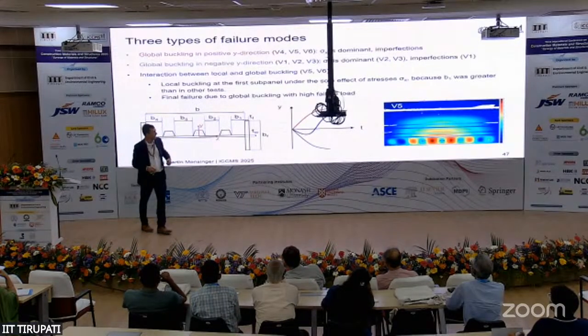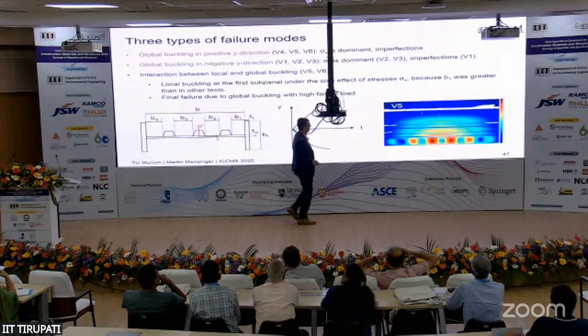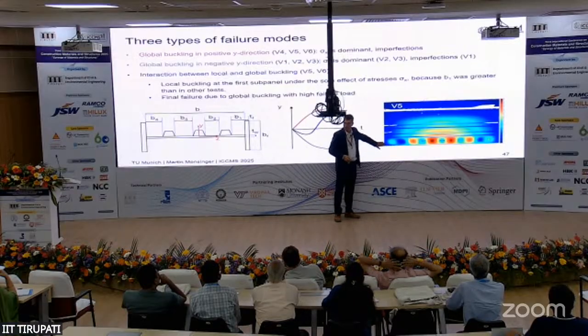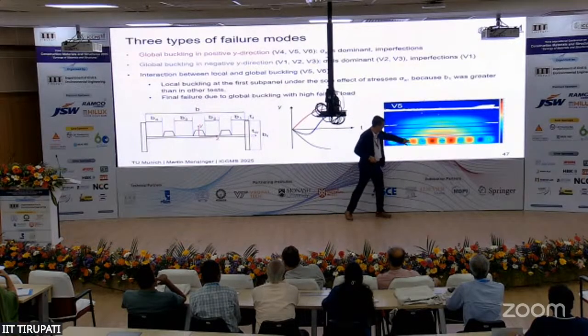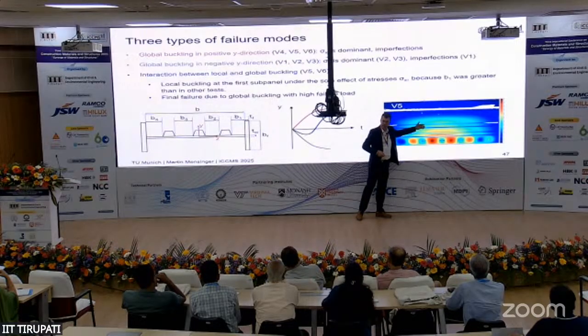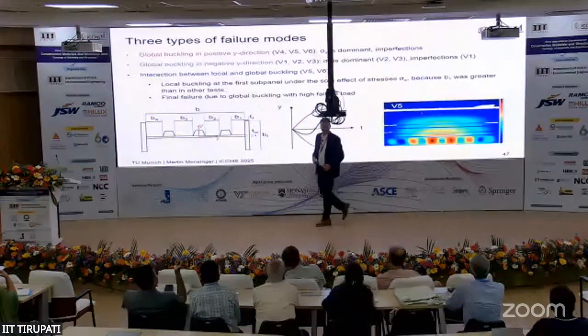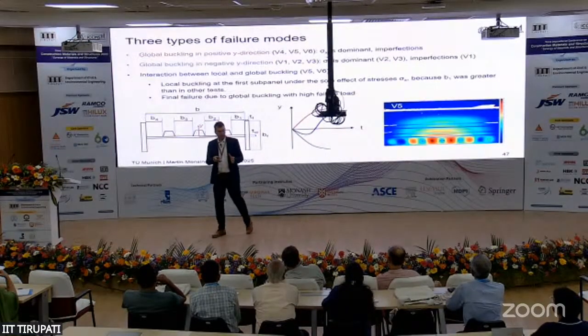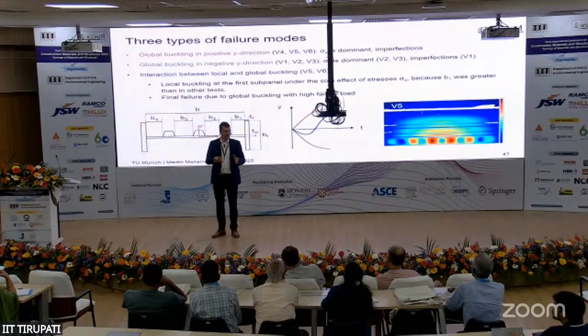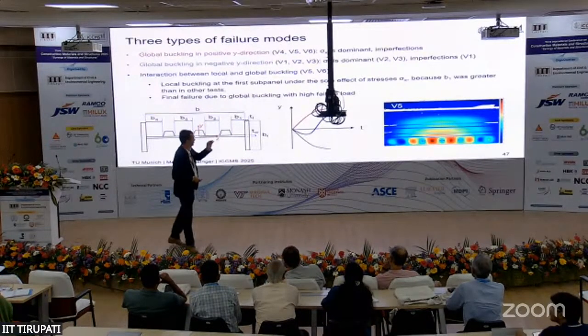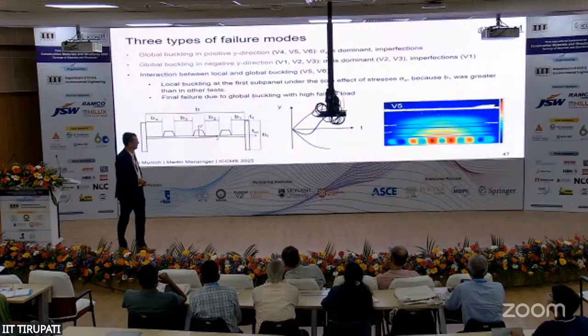And sometimes, as in the test we just observed with a short video, we have this situation that we have this multi-wave pattern in the lower buckling field, which stabilizes the panel and will help to increase the bearing capacity in cross direction. I'm not sure if we should consider that in the real design, because due to welding imperfections, we may have the situation that in certain cases this pattern will not occur in reality. This depends on the welding imperfections.